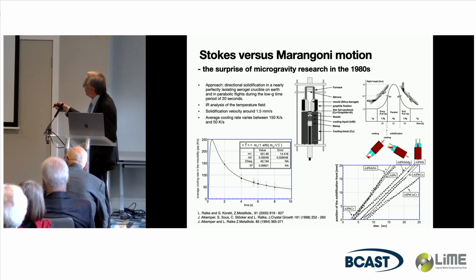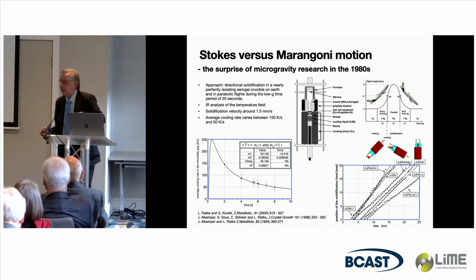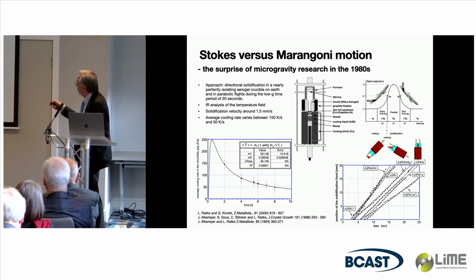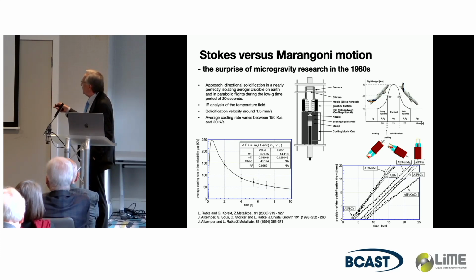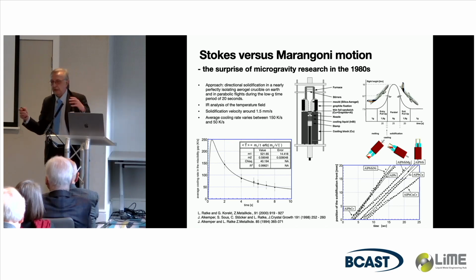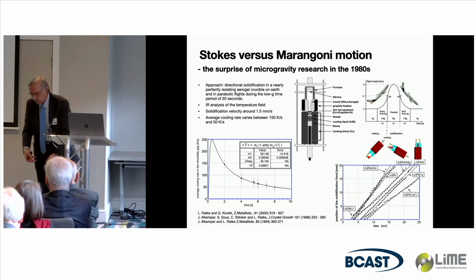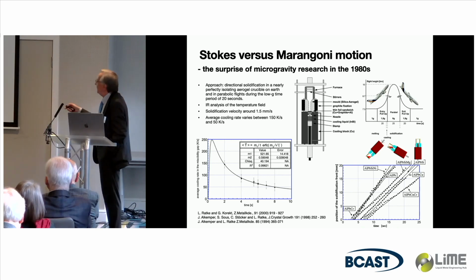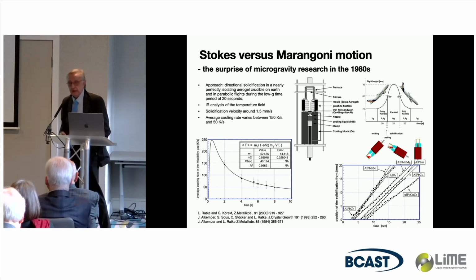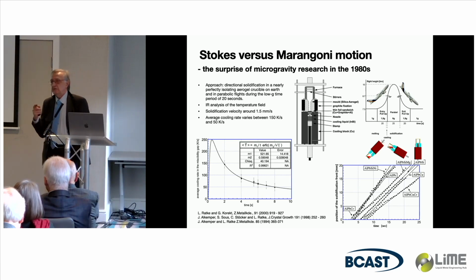Very simple. We take a furnace, cast on Earth the alloy in there. Then in space, so if we are here in this phase, you heat it up, have a stirrer in there, because with immiscible alloys, you cannot wait until diffusion does the mixing. So you stir it. Then in exactly this phase, you turn this facility upside down so that the melt goes by itself with 2 times gravity into this mold. It's a mold made out of silica aerogel, because the silica aerogel has a thermal conductivity of 20 milliwatt per meter Kelvin.